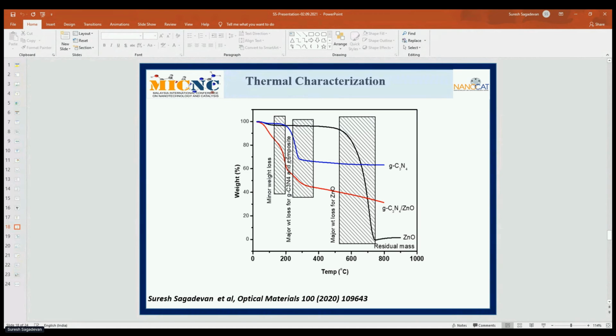You can see at this 180 degrees, a minimum weight loss is occurring for all three samples, which means the loss of hydroxyl groups and water moiety. In the case of zinc oxide, the significant weight loss occurred in the region of 550 degrees Celsius. You can see the major weight loss of zinc oxide at 550 degrees Celsius. This may be a phase change occurring, since the as-prepared zinc oxide sample also contains some amount of zinc hydroxide due to its contact with water moisture. During heating, the sample attains the major weight loss to form zincite as a more stable form, and the remaining portion is the residual mass.